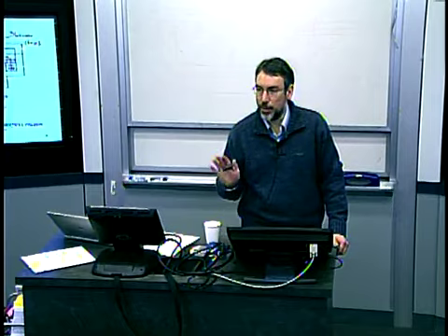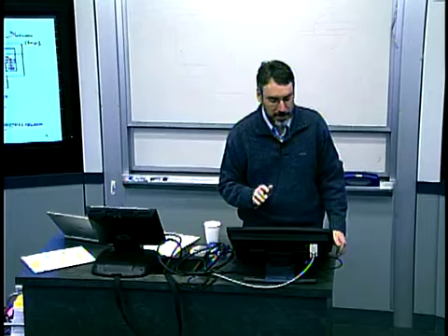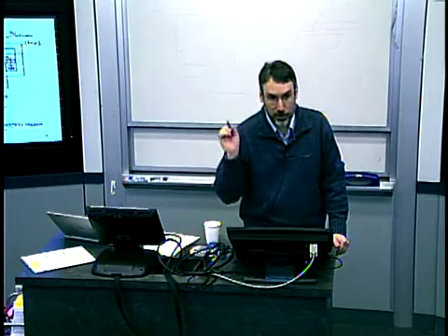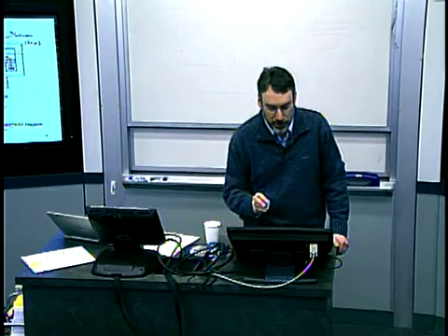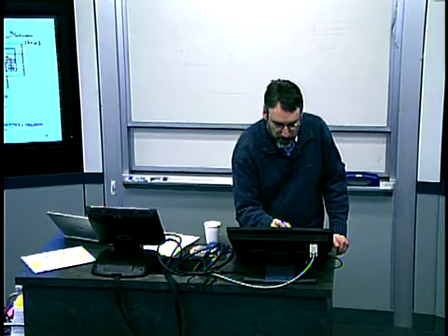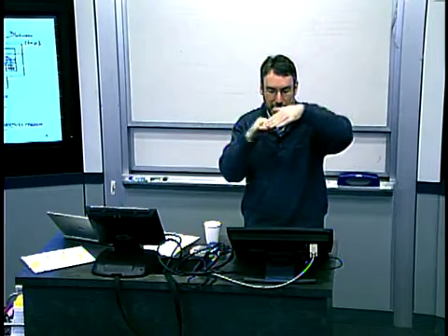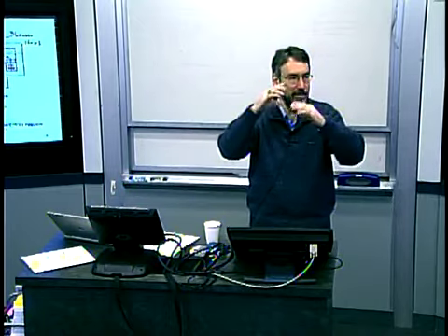So some of the key inputs, there's lots and lots of knobs to control on this equipment. Some of the key inputs that are used in this study, in the paper that we're looking at, are gap space, temperature, H2 pressure, and WF6 pressure. So the gap space refers to, I believe, essentially the height of this susceptor. One can play with the distance between the gas inflow and the wafer, moving it between, say, 2 to 4 or 5 inches.